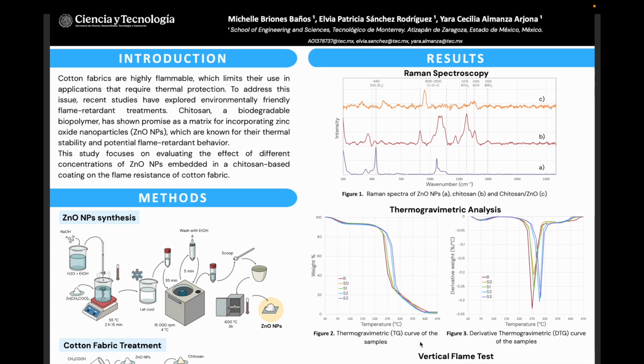And for the results, the Raman spectra showed the characteristic band of zinc oxide at 440 inverse centimeters, confirming its presence. Additionally, shifts and changes in intensity were observed in the carbon-oxygen-carbon band and other chitosan-related peaks, suggesting interactions between zinc oxide and chitosan rather than simple physical mixture.